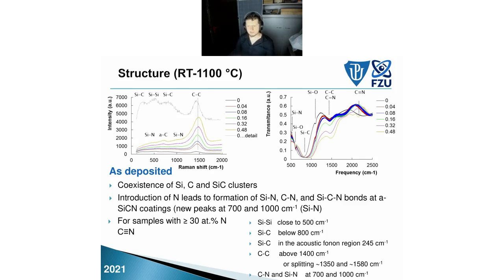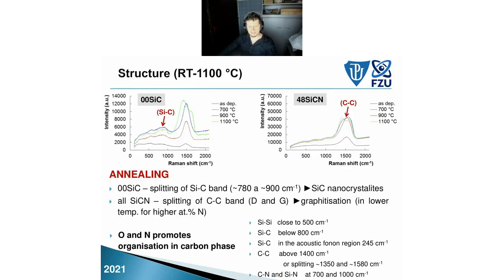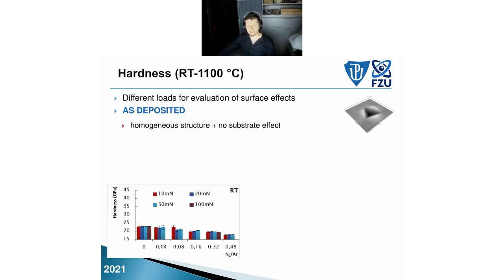Structure: generally it's an amorphous structure, and the introduction of nitrogen leads to the formation of Si-N, C-N and SiCN bonds. After annealing in pure silicon carbide, there is a creation of silicon carbide nanocrystallites. So it's not full crystallization, it's a partial crystallization into silicon carbide nanocrystallites. And in silicon carbonitride, there is a splitting of the carbon-carbon band, a graphitization. So we can see that oxygen and nitrogen promote organization in the carbon phase. And what does it mean for mechanical properties?